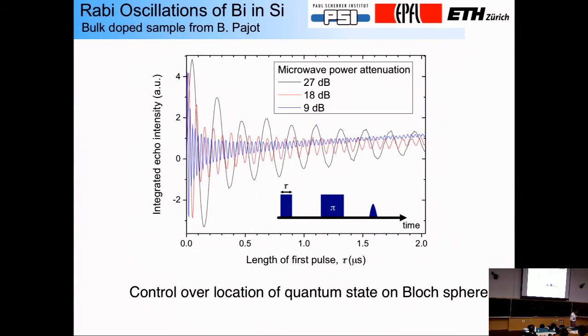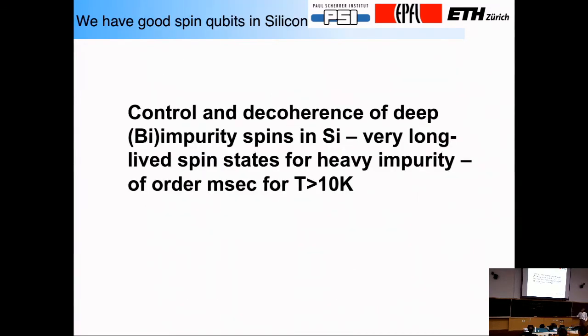And of course, you can not only look at this, you can show, using, for instance, Rabi oscillations, that you have a Bloch sphere at all. Rabi oscillations just show you that a pi over 2 pulse does the same thing to the system as a pi over 2 plus 2 pi n, where n is an integer. And so what this means is I can set any quantum state that I like on the sphere by appropriately choosing microwave pulses. Okay, so basically we have control of decoherence of deep impurity spins in silicon. So this big atom has very long T2 times of the spin, and we have this ability to control that state. So that's very promising.